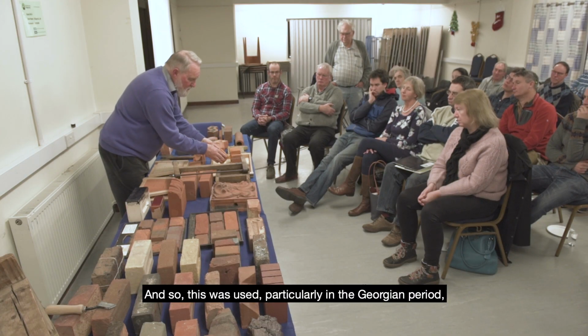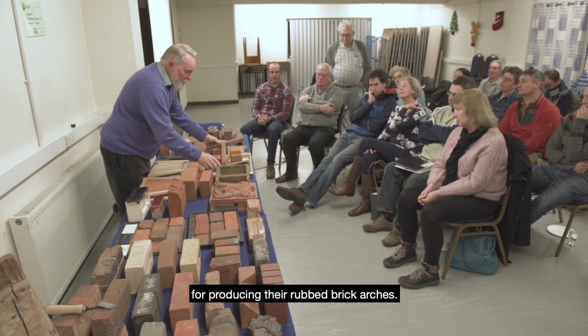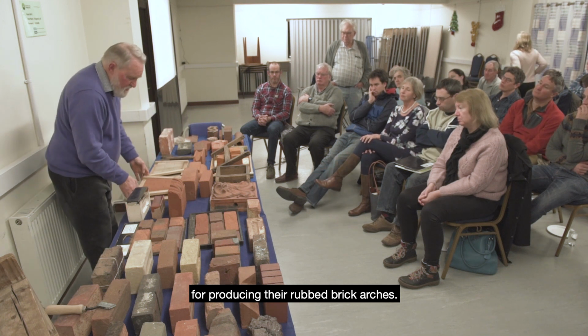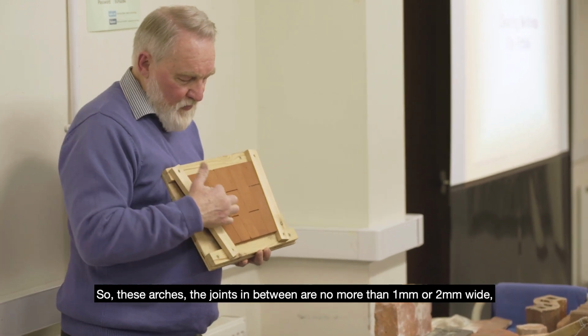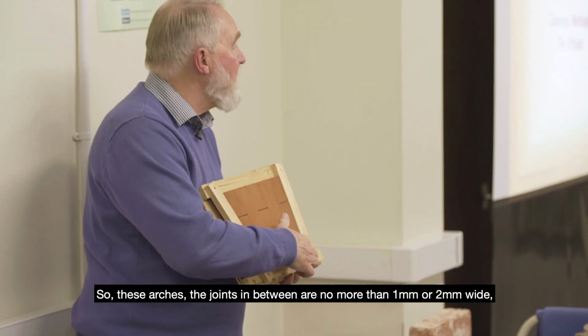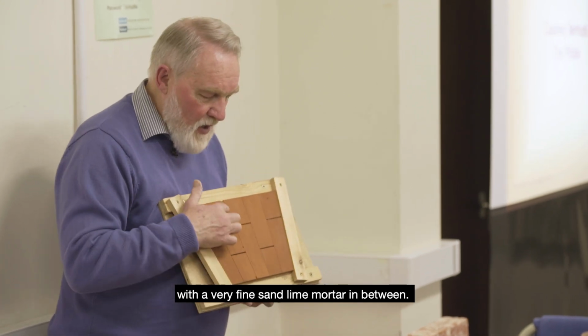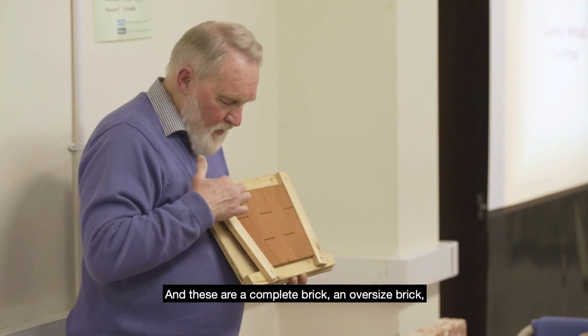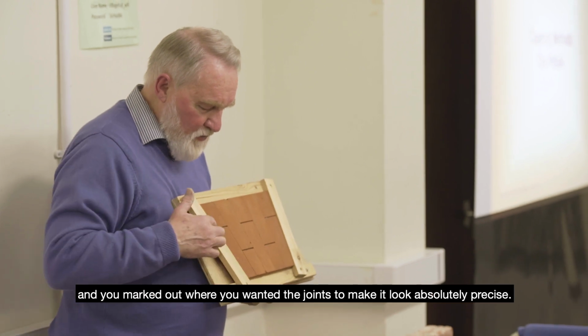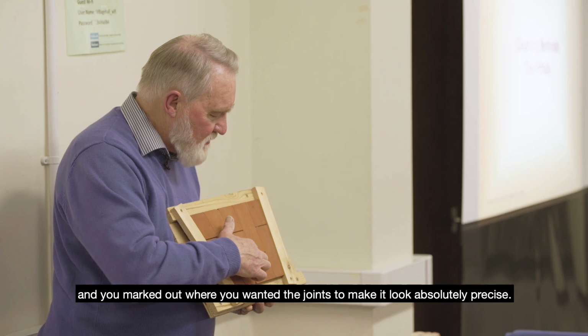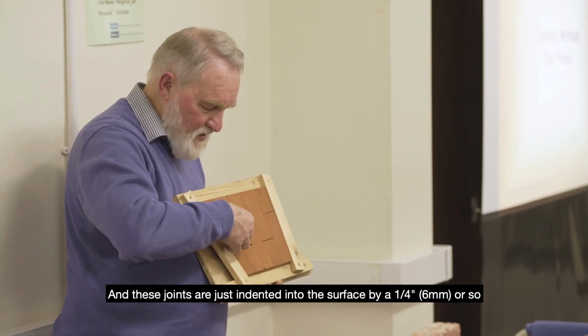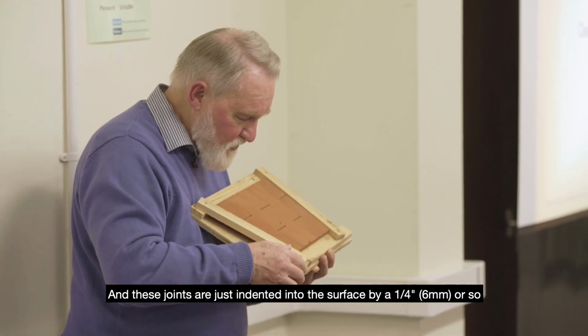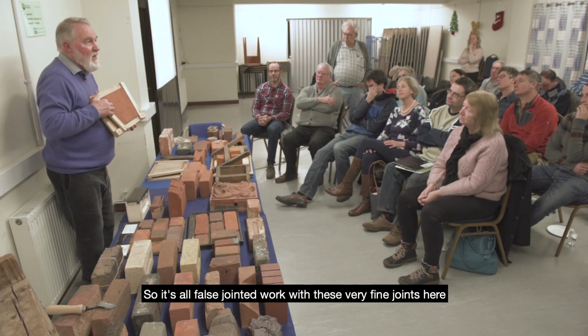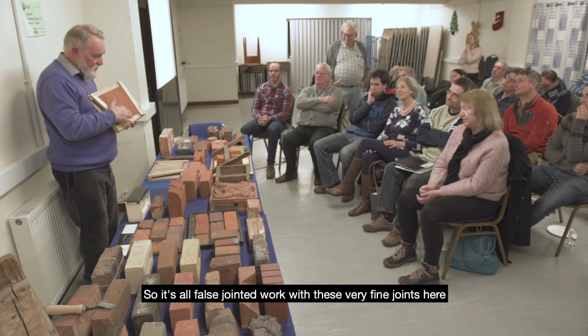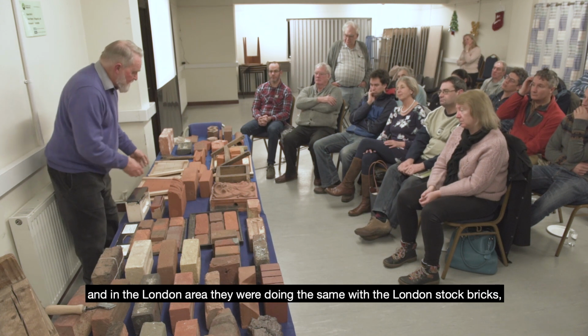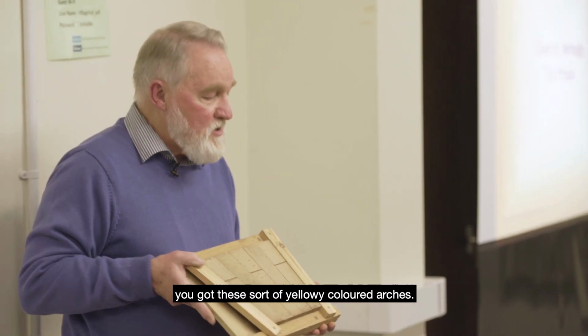And so this was used, particularly in the Georgian period, for producing their rubbed brick arches. So these arches, the joints in between, probably no more than 1 or even 2 millimetres wide, with a very fine lime, sand lime mortar in between. And these are a complete, oversized brick, and you marked out where you wanted the joints to make it look absolutely precise. And these joints are just indented into the surface by a quarter inch or so, and then you tuck your lime mortar in. So it's all false jointed work with these very fine joints here. And in the London area they were doing the same with the London stock bricks. You got these yellowy coloured arches.